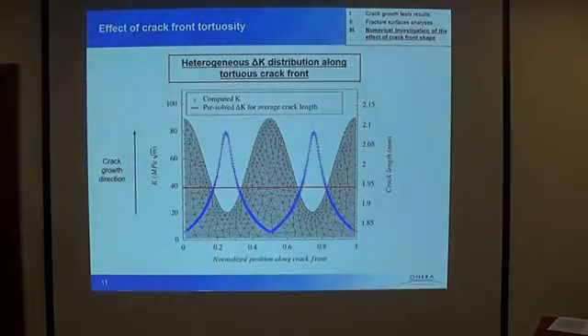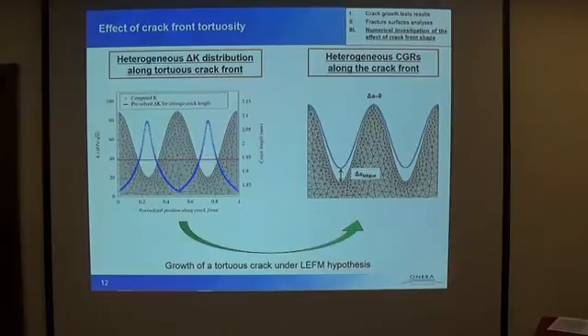But first, let's have a look at the delta K distribution along such a crack. You can see that in the depth of the tortuosity, you get some very high delta K value, while at the top of the tortuosity, the delta K value is almost 0. And we can compare it with the assumption of a straight through-thickness crack of average depth of 2 millimeters. So assuming, once again, a simple Paris law and linear elastic fracture mechanics, we see that the crack tortuosity will unfold.